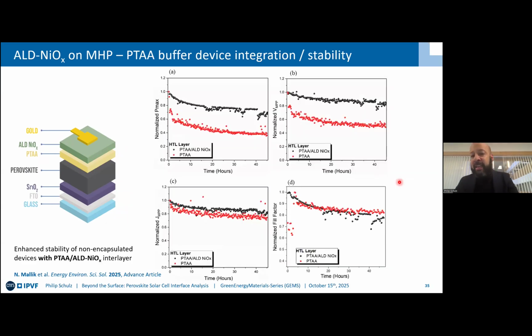Does it actually aid to some extent to cell stability? And yes, even if this layer is very thin, you can see that if you had only this PTAA layer, you see this initial drop, eerily similar to what we had seen in the past on the spiro-OMeTAD gold surfaces, indicative of gold migration into the layer. And this is effectively inhibited once you have the ALD nickel oxide layer on top.